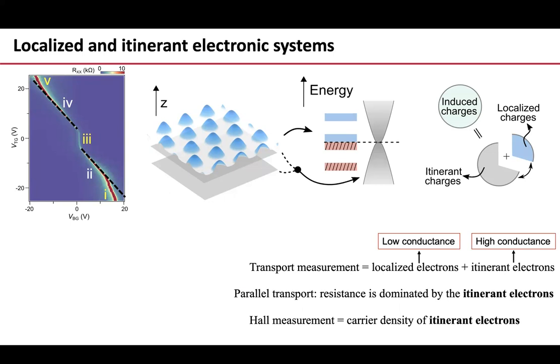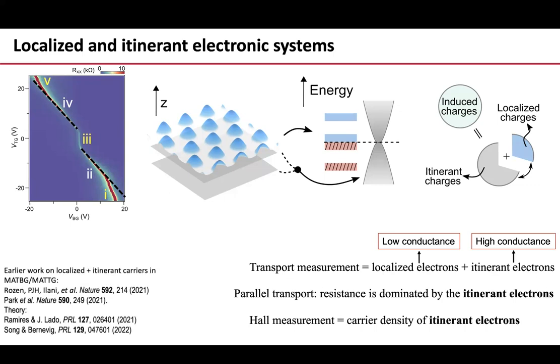If we do a Hall measurement, which is what I'm going to show you in a moment, we are also only sensitive to the itinerant electrons, because a Hall density measurement tells you the density of itinerant carriers that are moving in your system. And as I mentioned, there was already this idea that we may have two types of electrons, localized and itinerant. It's not completely new and crazy. There's plenty of evidence from other experiments where they thought that this might be happening. But I'm going to show you now a more dramatic manifestation of this.